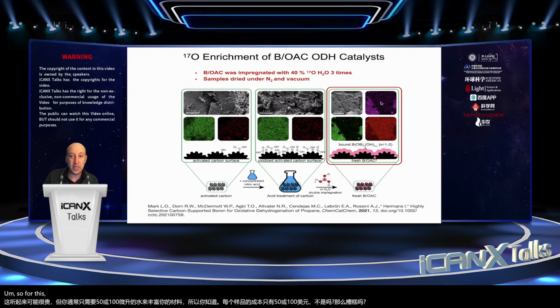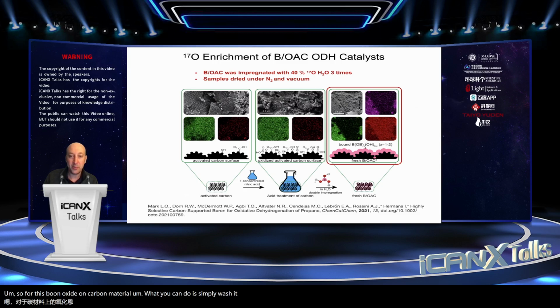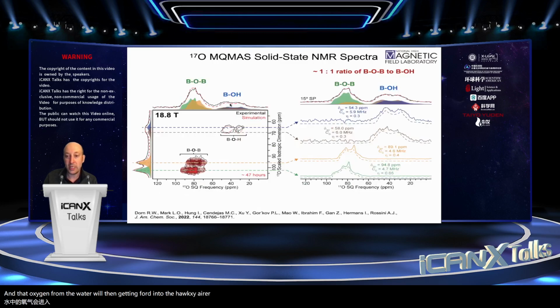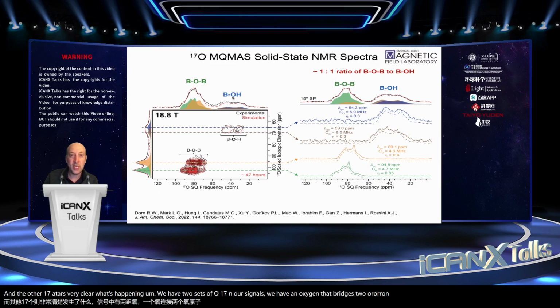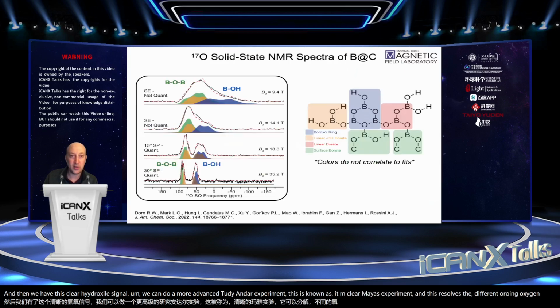So for this boron oxide on carbon material, what you can do is simply wash it repeatedly with a bit of O17 water, and that oxygen from the water will then get incorporated into the oxide layer. So now we can do the O17 NMR spectrum, and the O17 NMR is very clear about what's happening. We have two sets of O17 NMR signals. We have an oxygen that bridges two borons, and then we have this clear hydroxyl signal. We can do a more advanced 2D NMR experiment. This is known as an MQMAS experiment, and this resolves the different overlapping oxygen signals.